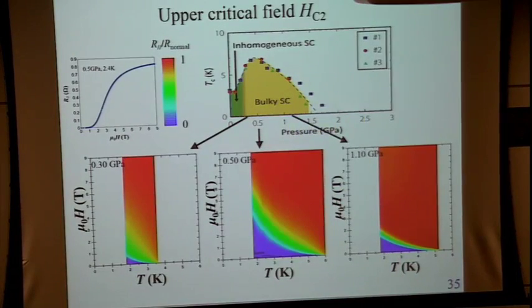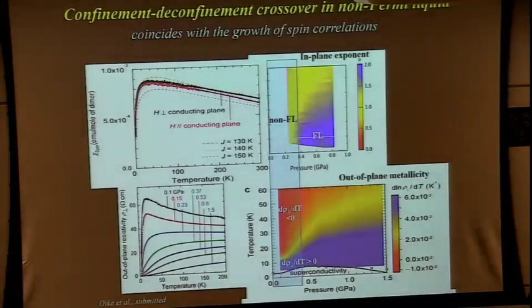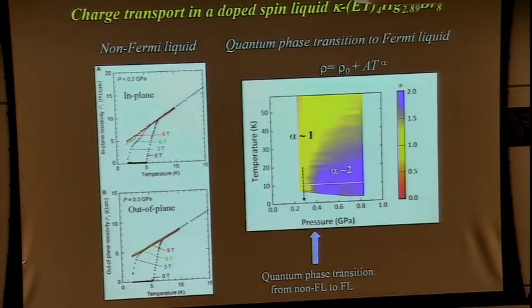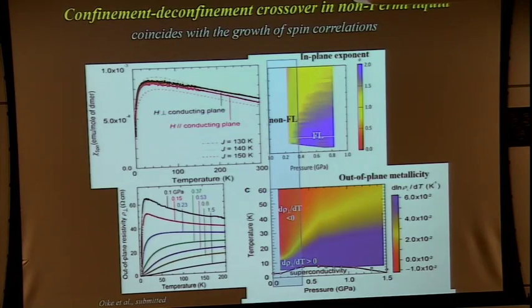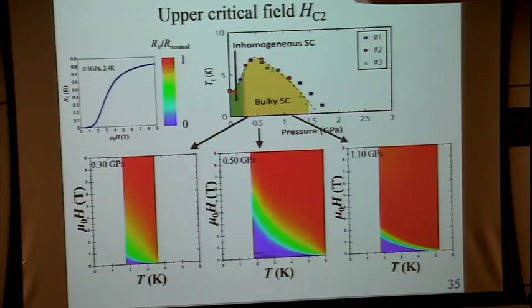So one interesting point. This shows superconductivity as a function of pressure. And interestingly, the Tc forms a dome, and the maximum occurs around 0.5 GPa. Roughly occurs here, maybe 0.4 or something like this. Around these pressures, Tc may be maximized.